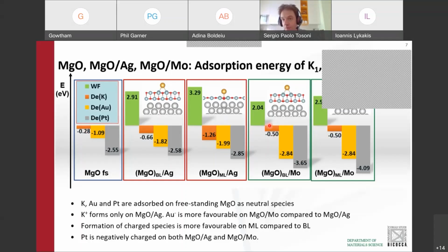Why? Because gold is much more, of course, electrophilic than potassium. It likes to be stabilized as an anion, as gold minus. And this is easier if the work function of the substrate is smaller. Small work function means shallow donor states in the substrate. It is easy to extract one electron and transfer it to the adsorbate.